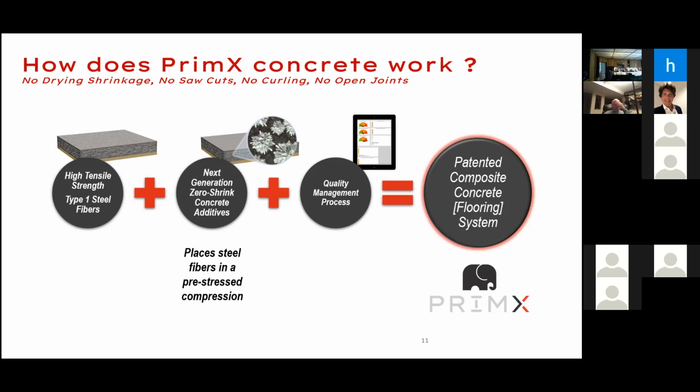And when that concrete is set, a day or two after it has completely set, that nothing can move, it's not plastic anymore, it expands, except that concrete is now very heavily internally restrained. Now you have an expanding concrete body that is internally restrained. That is going to cause for that concrete body to be self-stressing. In other words, to accommodate pre-stressing, to essentially, from the start, be pre-compressed. So that's why we call this chemical post-tensioning. It is a form of post-tensioning, except you are not using steel cables, if you're familiar with cable post-tensioning indeed.